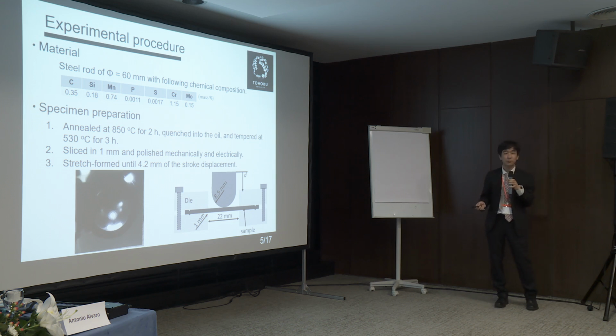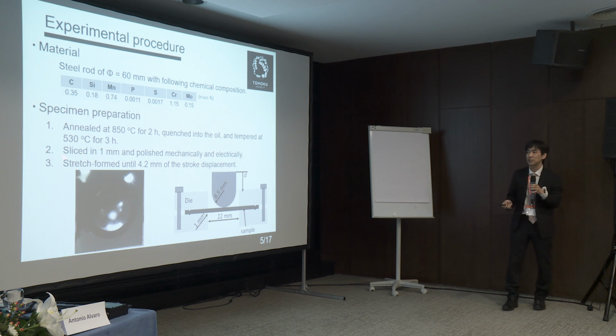These are the experimental procedures. We used tempered martensite steel rods with 60 millimeters of diameter, and the chemical composition of the material is shown in this table. The rod was annealed at 850 degrees for 2 hours, quenched into oil, and tempered at 530 degrees for 3 hours. The rod was sliced to 1 millimeter and polished mechanically and electrically. After that, the sheet was stretch formed with 4.2 millimeters of stroke displacement by using a universal testing machine.